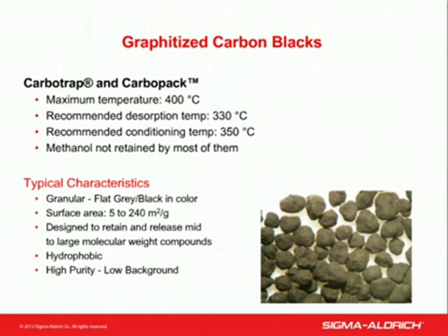Most of the Carbopacks, except Carbopack X and Z, are non-porous. Since most graphitized carbons don't contain any pores, adsorption takes place by London dispersion forces, which exist between the molecules and the adsorbent. Carbopack X is one of the strongest graphitized carbons, which bridges the gap between the other Carbopacks and porous polymers and the stronger carbon molecular sieves.